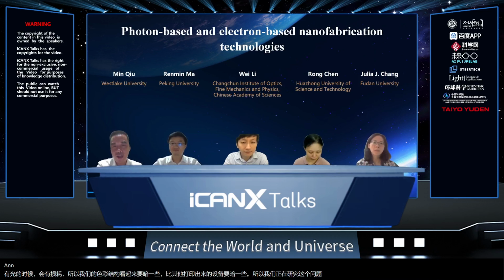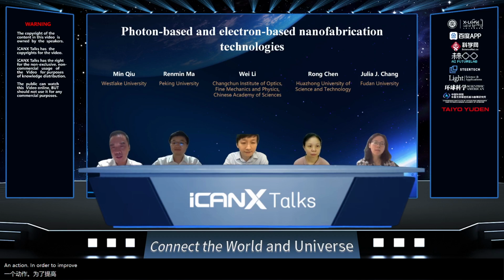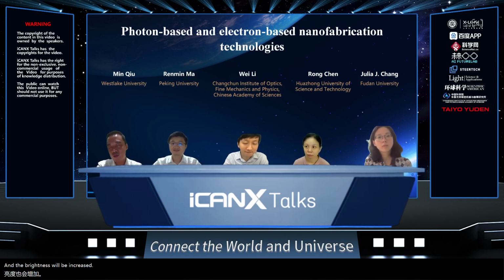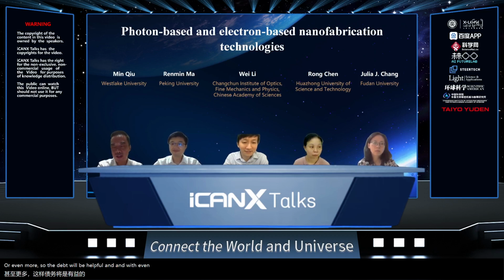And actually, in order to improve this, the best way is to reduce the thickness of the film. We have roughly 50 nanometers. If we can reduce it to 20 nanometers, the brightness will be increased at least twice or even more. So that will be helpful. And with even thinner films, the angular independence will be even better.